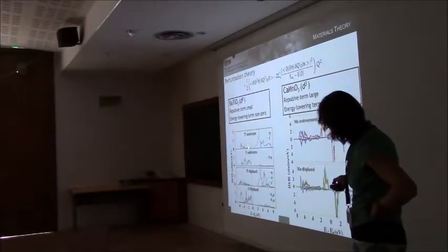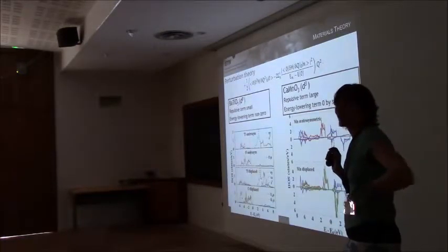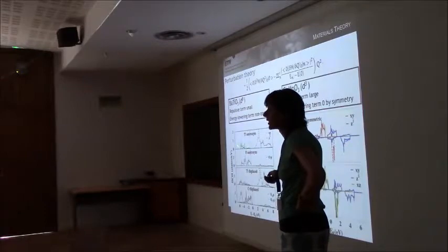This line is the Fermi energy. When we say that titanium is d0, then we're kind of lying. It's titanium 4+, so formally it's d0. But if you look at the density of states, there's actually quite some electron density on the titanium already, even in the centrosymmetric state.